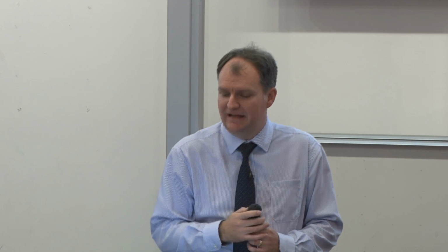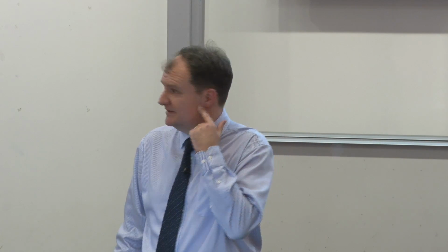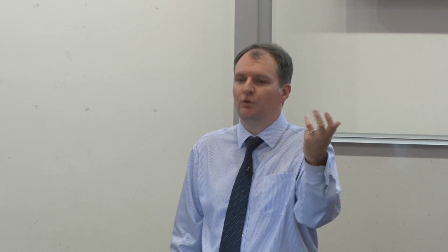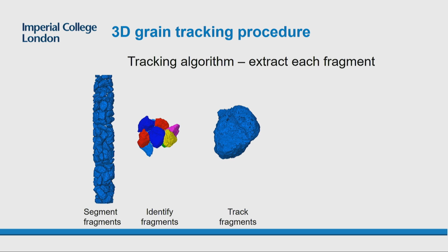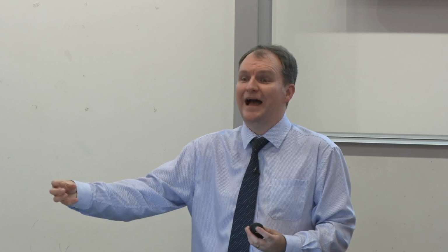And the challenge then was to actually track this performance. It's all very well just seeing nice images of what's happening. We wanted to actually quantify what was happening. And so we developed a new algorithm for doing this. First stage was to separate all these individual rock particles out, which is nice and easy at the very beginning of your leaching. The problem is as the leaching goes on, various minerals start depositing at the points where your rocks touch one another, which makes it harder to segment the individual rocks as time goes by, because this new added mineral doesn't look that different to the existing mineral.